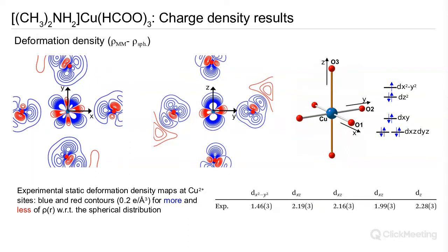And it's really beautiful. What you see appear is these dz squared minus r squared orbitals, or shapes that look like those orbitals, appear along z in the blue, which we anticipated to be doubly occupied. And then on the left-hand figure here, we can really see the dx squared minus y squared orbital in red, which has only got 1 electron in it rather than 2.